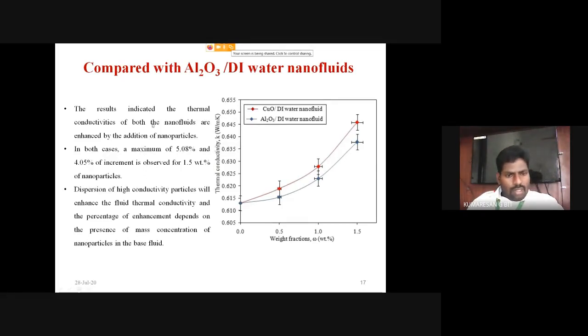But in both the cases, a maximum of 5.08 and 4.05 increment is observed for the 1.5 wt.% of nanoparticles. This is because of addition of the high volume or weight concentration of nanoparticles in the base fluid. It will linearly increase the thermal conductivity of the working fluid. Then dispersion of high conductivity particles will enhance the fluid thermal conductivity, and the percentage of enhancement depends on the presence of mass concentration of the nanoparticles in the base fluid.